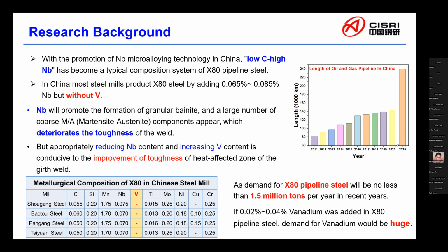Recent research results of our team show that reducing niobium content and increasing vanadium content is conducive to improving the toughness of the heat affected zone of the girth weld. So we can make an assumption that niobium content in the pipe would be reduced, and niobium plus vanadium composite microalloying would be used to guarantee the high strength, meanwhile increase the toughness of the weld. As demand for X80 pipeline steel will be no less than 1.5 million tons per year in recent years, if 0.02% to 0.04% vanadium was added in X80 pipeline steel, demand for vanadium would be a huge number.